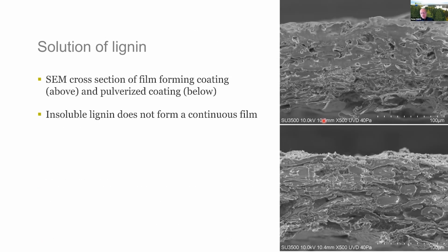If we look at the next picture here, we actually see that when we had the solvent system, we have a nice melting of the lignin structure here. This is just plain lignin-based lignin after drying, evaporating the solvent. If you have an insoluble system, you get something that looks like this, quite a lot of dusty surface that would actually fall off in dust. And I haven't had anyone say, hey, I have a pile of money, I want you to create dust, at least not in paper. In the paper industry, you usually want to get rid of that.